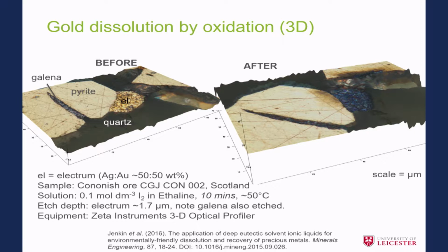Okay, so we can see here a pit now where the gold has dissolved away. And our microscope is measuring that surface very precisely. So we can subtract one from the other and measure the depth of that pit, 1.7 microns. And this allows us to measure the rate of dissolution.